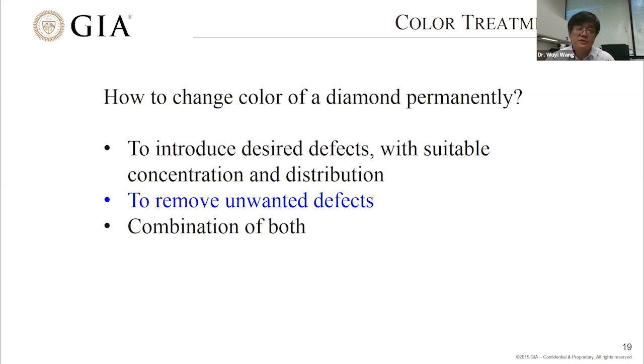Of course, that's very important. We don't want it to be too dark or too light. And also the distribution is important. We want the color to be evenly, or as much as possible, evenly distributed. Or we remove the defects that we don't like, like the brown color. It's due to vacancy clusters. There's a technique we can use to remove the vacancy clusters to reduce the brown color, so to remove the unwanted defects, or a combination of both. So that will give us more options.